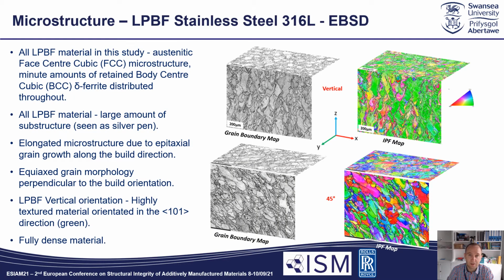In terms of the microstructure, what we've got here are the EBSD maps for both the vertical material, so the top images, and the 45-degree samples given at the bottom. So in either case, the grain boundary maps for each variant are given to the left, and the inverse pole figure map to the right. In both cases, the material is predominantly made up of an austenitic FCC microstructure with a very, very small amount of retained BCC ferrite distributed at some of the grain boundaries.